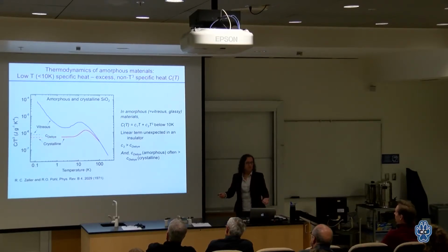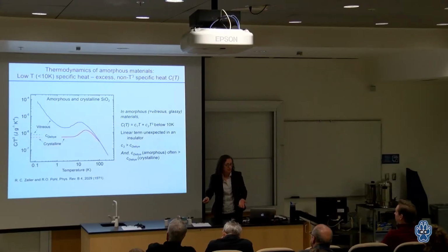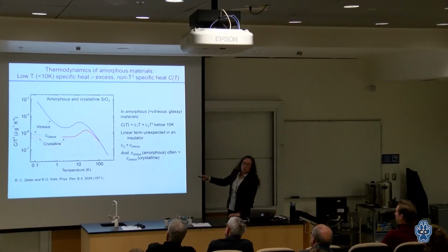So there's a theory for this, it's called the Debye theory of heat capacity. You make the amorphous material, and you can see the sound velocity is a little different. Sound velocity is a little lower, which leads to a little higher heat capacity. It's that blue line. But this is not only not coming into it, it's turning the other way.